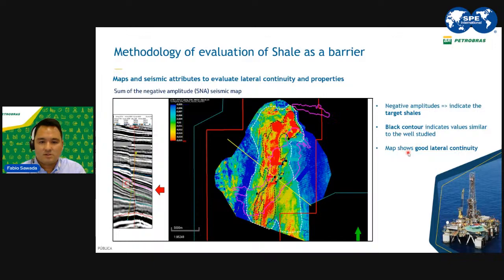Okay, so the map is showing that we have a good lateral continuity of the shale, and this shale goes beyond the limits of the field that we were studying. So we could use this to map the shale in other neighbor fields. This brings a very good potential. We could increase the radius of the seismic, and we could use the same seismic attribute to map this around many fields that are close to this one and that have the presence of the same shale as interval C.